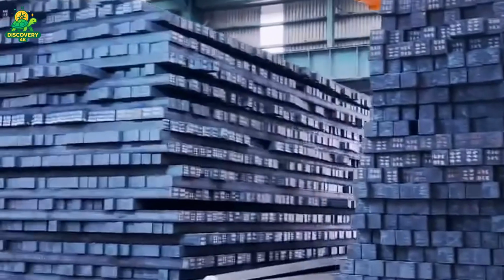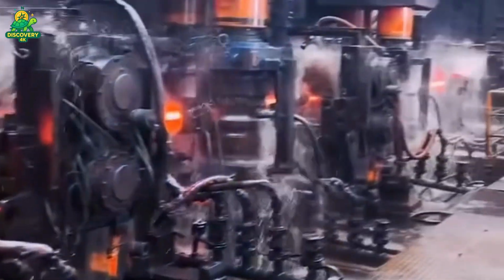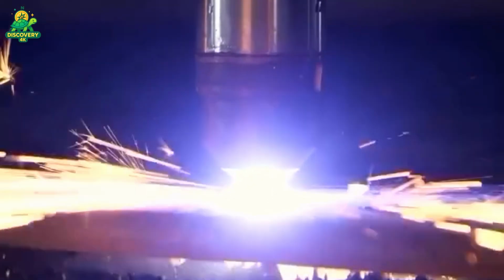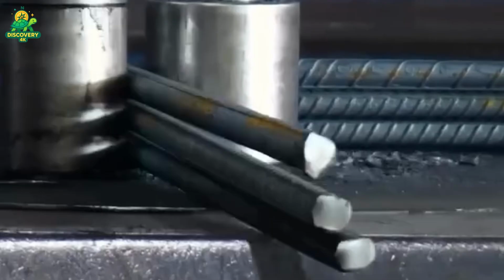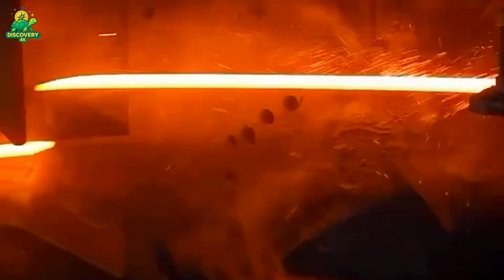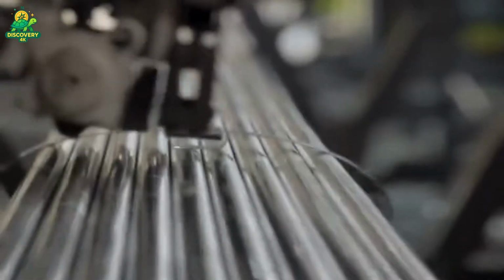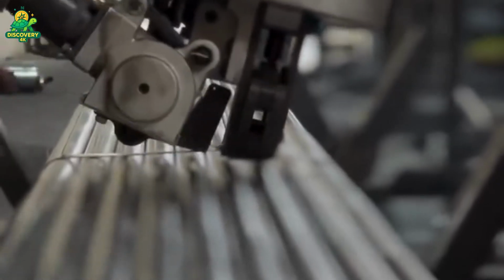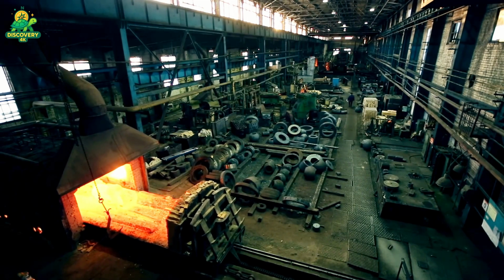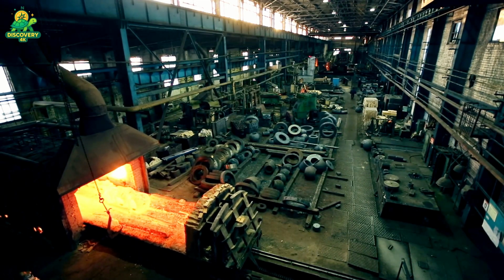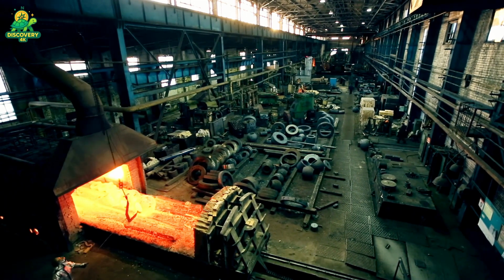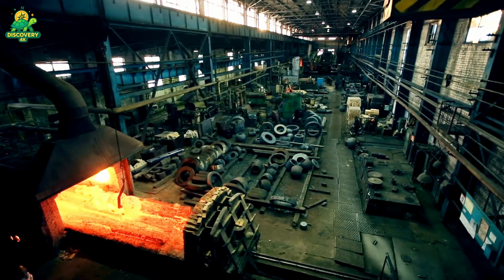This is where the transformation really takes shape. The billets re-enter a reheat furnace to bring them back to a pliable temperature. From there, they're fed through a series of rolling stands that progressively shape them into long, slender rods, each one with a ribbed surface to help concrete grip the steel. The ribs are not just aesthetic, they're engineered for maximum adhesion in concrete. Depending on the final use, the rebar is rolled into different diameters, typically ranging from 3/8 inch to number 18, 2.257 inch. The rods are then cut to standard lengths, usually 20 or 40 feet, and moved to the cooling bed.